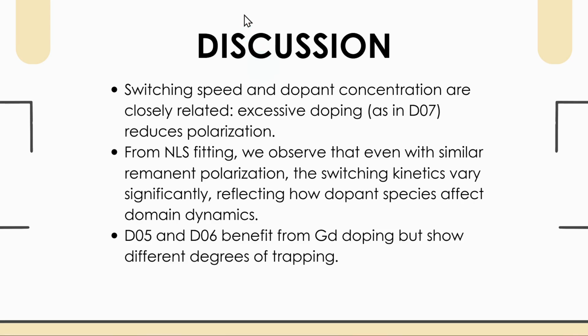And discussion. This project shows that the dopant type and amount are very important. Even if two samples switch the same amount of charge, one might do it faster than the other. D05 was the best because it had high polarization and fast switching, which are both important for memory. The NLS model helped us quantify the speed in a more scientific way.